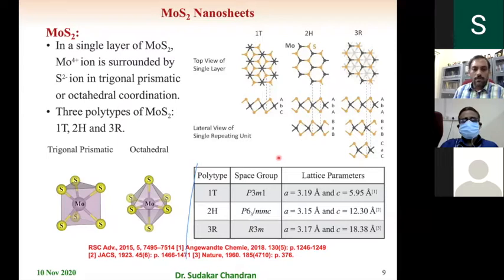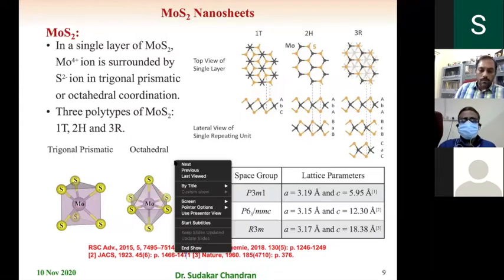There is also another phase which is called 1T prime. The 1T phase itself is not stable at room temperature. The 1T prime has a distorted octahedral geometry. Generally, in 2H and 3R, the molybdenum occupies the trigonal prismatic coordination site, whereas in 1T, the molybdenum sits in the octahedral site. When the phase transition from trigonal prismatic to octahedral happens, there is a reorientation of the sulfur atoms, and therefore the trigonal prismatic can convert to the octahedral phase. That happens at high temperatures.